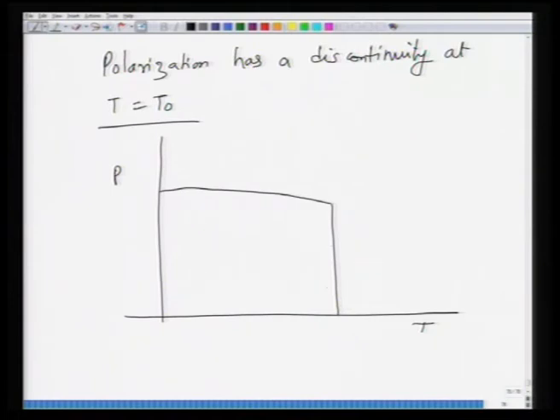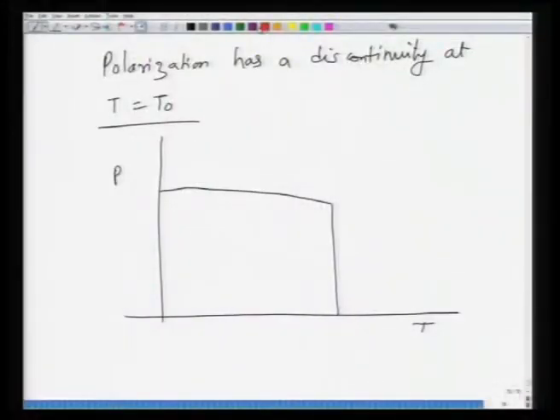So this is a discontinuous transition, and susceptibility also follows a similar trend, showing a discontinuity at this temperature. So basically the susceptibility will show a transition like this, with this discontinuity here. If you extend this line, and if this point is not T naught, this becomes Tc.